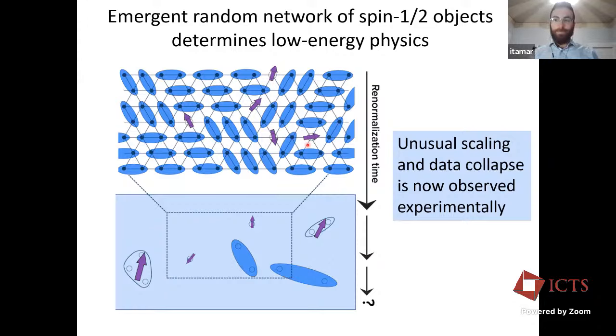I see one raised hand, Sumiran. Yeah, please go ahead. Hi, this is Sumiran from IIT Bombay. We applied this scaling collapse to a copper-based magnet with titanium disorder. It was quite disordered, 50-50%, in collaboration with the Mahajan group here and the Sharma group at IISc. The technical thing we noticed is that when we did the collapse for the as-measured specific heat and the magnetic specific heat, the gamma estimate was close but far enough apart within error bars. In your Nature Communications paper, it was the as-measured specific heat in some of the plots. Do you have any comments on that?